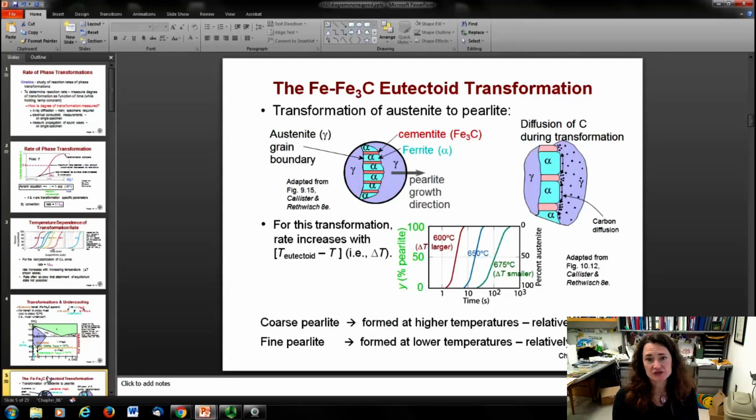What happens as you do that, to form the pearlite, is that you get these lamellae of the cementite and the alpha phase in regions. Usually this starts at a grain boundary, okay? It starts at a grain boundary and it grows outward into pearlite from austenite, okay? And that happens by diffusion. So you have the diffusion mostly of carbon. It diffuses faster and the carbon moves around. The cementite has a higher concentration of carbon, and so it moves to the cementite phase right there.